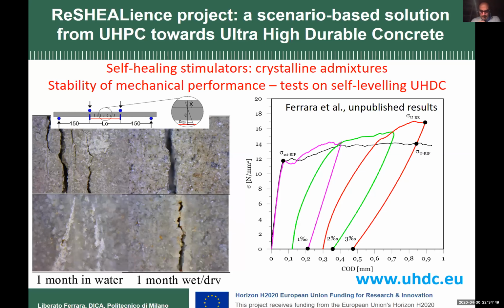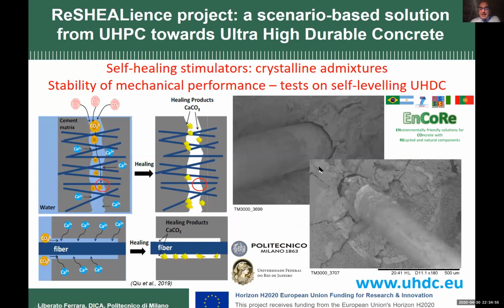We also observed that it's not only closing the cracks, but also at the level of the fiber-matrix interface, there is a deposition of products along the interface which really improves the fiber-matrix bond and enhances the toughness and performance of the material.